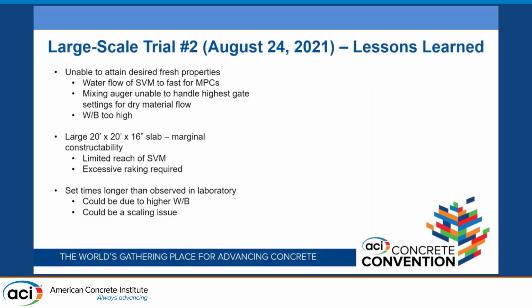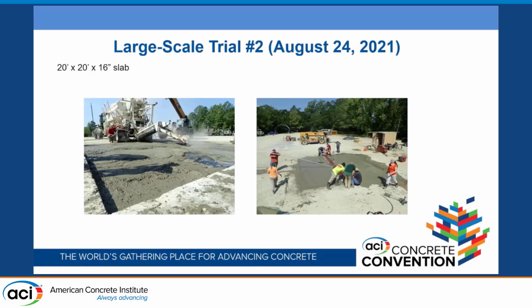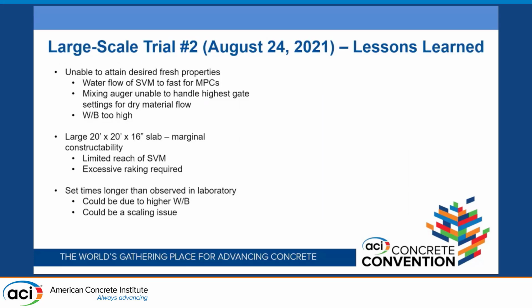Yes, we stubbed our toe pretty good, but I will say pay attention to this date. It gets exciting pretty quick. But one of the determinations was 20 by 20 was unfeasible. It's just too physically taxing. If you look in that picture, that's probably 2/3 of our group that was out there, and we were worn out. So it's probably from a constructability standpoint too much. Set times were longer than observed in the lab. Well, that was because our water was too high. And then also there could be a scaling issue.